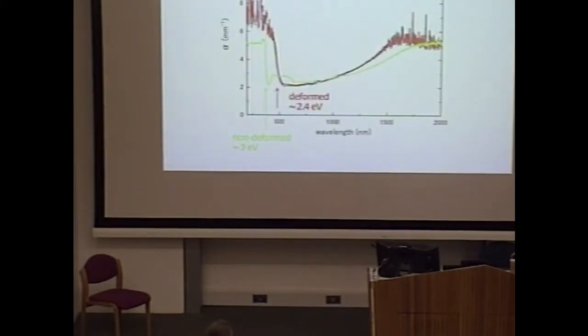And this is the optical absorption spectra of deformed silicon carbide. So deformed crystals, non-deformed crystals, the band edge is here. And in the deformed case, the band edge changes to this position, around 2.4 electron volt. So this color change can be understood like this.